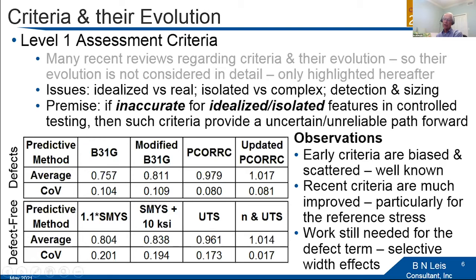If we turn our attention now to defect-free pipe, remembering that the failure pressure is a function of the pressure of failure of the pipe that's defect-free, coupled with the effects of the defect, it becomes apparent that for these early criteria, much of the bias that's evident here is a consequence of the bias that's present in the reference stress. In comparison to that, if you look at the more recent criteria, you see that the bias is much reduced. And you see that the scatter is significantly reduced when we use a failure criterion for the reference pipe that's a function of the UTS and the strain hardening exponent. So the observations are as noted here. The early criteria were scattered. That's well known. The recent criteria are much improved. But if we dig into the details, we quickly see that there's work still needed in terms of the defect term, particularly in regard to selective width effects.